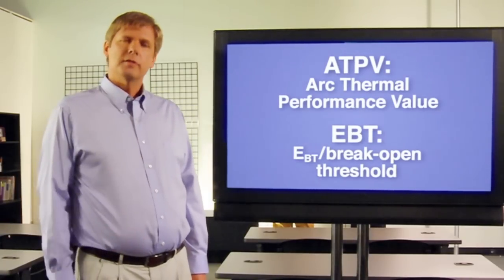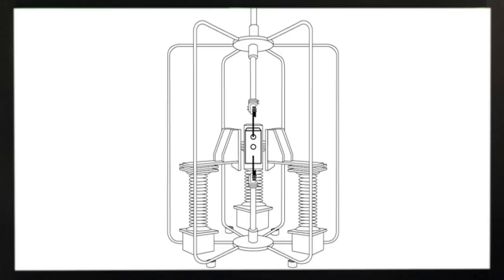Let's talk about how this test works. Three flat fabric samples are placed over three flat panels with heat sensors positioned 12 inches away from the center of these arc electrodes here.